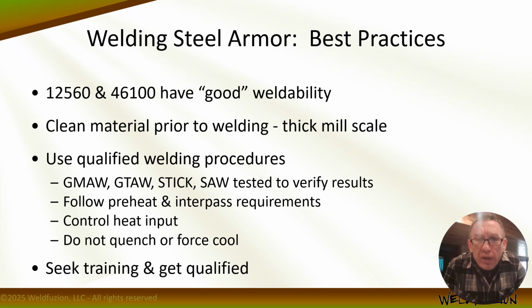Preheat is important. It eliminates moisture as a source of hydrogen, prevents thermal shock from welding, improves penetration, and slows the rate of cooling. Controlling preheat and interpass temperature will ensure that cooling rates are within limits and that temps haven't softened the materials. So it's really critical to monitor your temperatures.